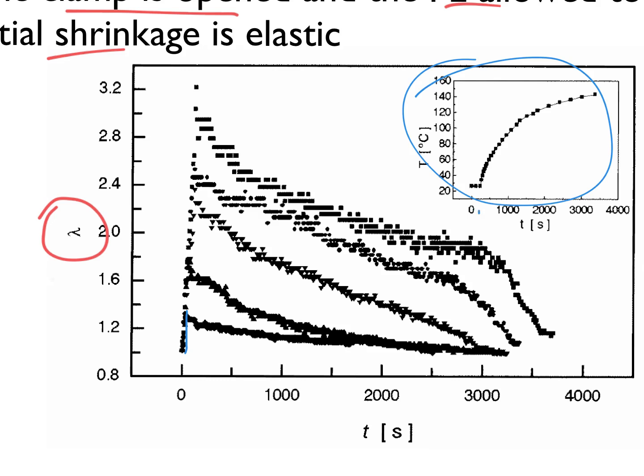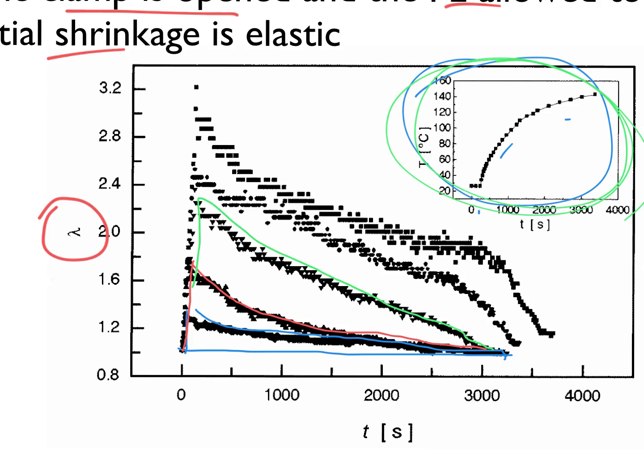All right, and so we're going through this cycle of heating that's pretty quick in the scheme of things, and during that cycle of heating it all drops back down, pretty much in this first case back to where it was. That's full elastic recovery. Instead you go to a slightly higher value of strain, or lambda is higher, and it kind of goes back as well, and then this third one eventually goes backwards. Now keep in mind, this is a lot of thermal annealing, if you want to call it that. You're giving a lot of time and temperature to recover like this.